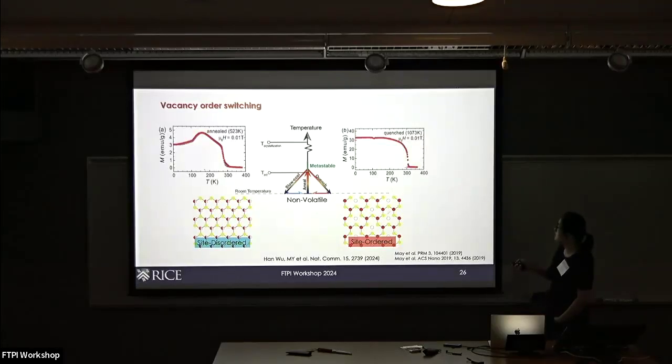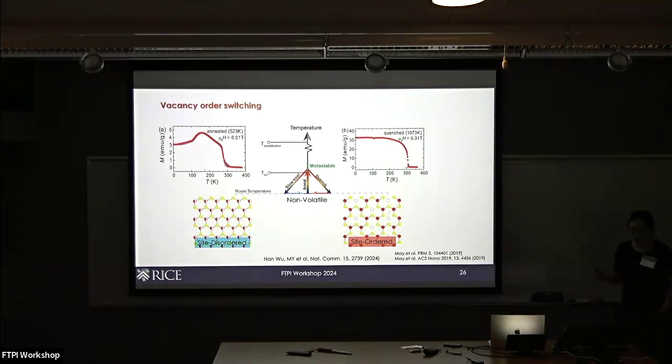Okay, so which phase you end up with affects the magnetization. This is magnetization measurements taken on samples that are quenched versus slow cooled. And here, there are a couple of differences. I'll come back to this curve at the end of the talk, but one obvious difference is there's a kink in this situation around 100 K. This is the impurity from the other phase, but I will come back to this much later. So this does affect the magnetization of the crystal.